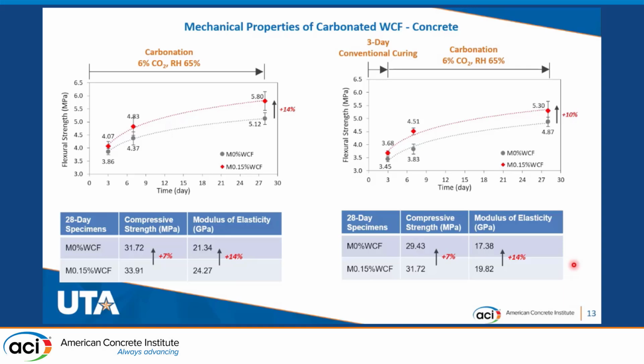Different carbonation regimes were examined for this study to optimize the carbonation method using the mechanical property results. Here I'm showing you results of the carbonation at 6% CO2 starting immediately after casting, in the left part of the slide, and the results of 6% CO2 carbonation starting 3 days after moist curing, shown in the right part. Both studies suggest that flexural strength, compressive strength, and modulus of elasticity are increasing due to carbonation approximately at the same rate. We did notice, though, that the 3-day moist curing regime was giving a little lower compressive strength, flexural strength values, and modulus of elasticity results.